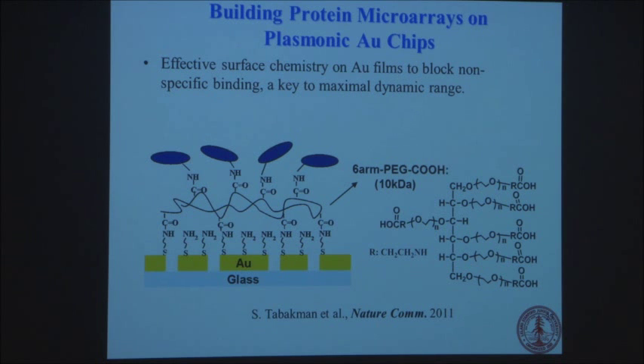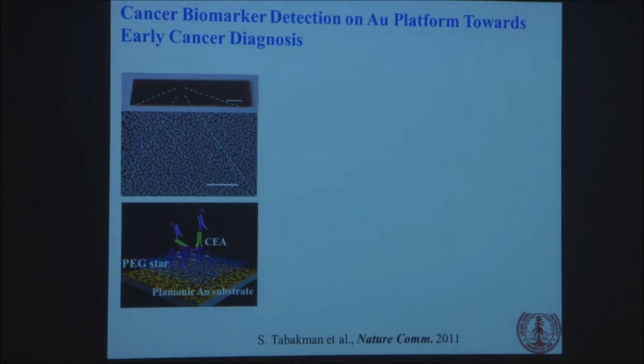And for chemists in the room, you know that on gold, the thiol chemistry is very well developed. So you can use it to coat the surface with all kinds of molecules to make it very good for capturing molecules for detection. And you can also block the non-specific binding very well using these polyethylene glycol hydrophilic chains. So the chemistry here is quite easy to develop on gold. It's actually easier than on glass. So let me show you a few examples of using them for detecting molecules.